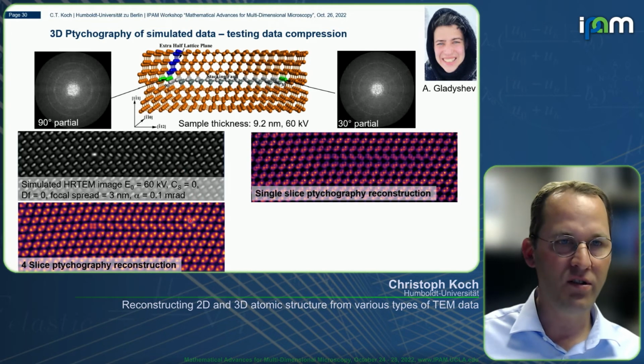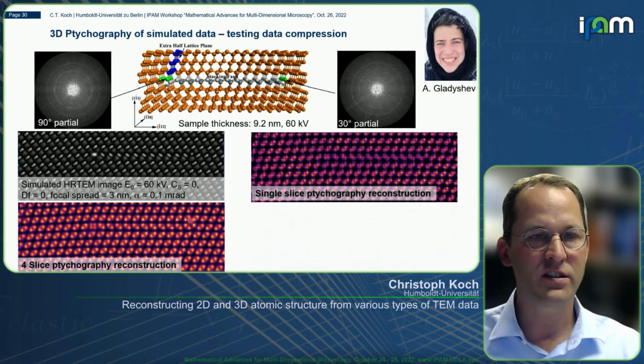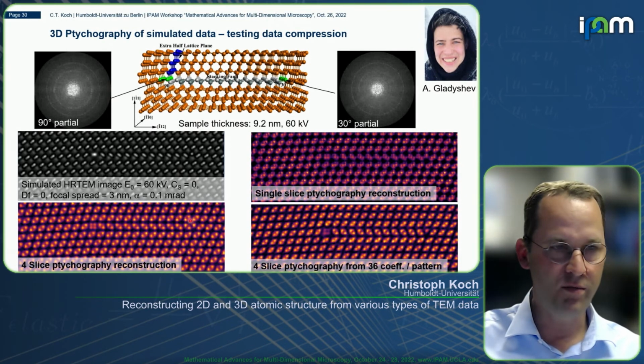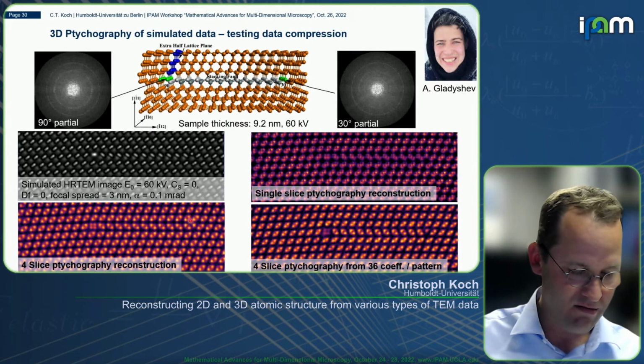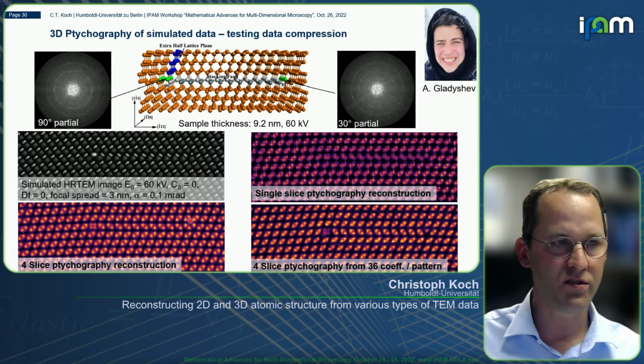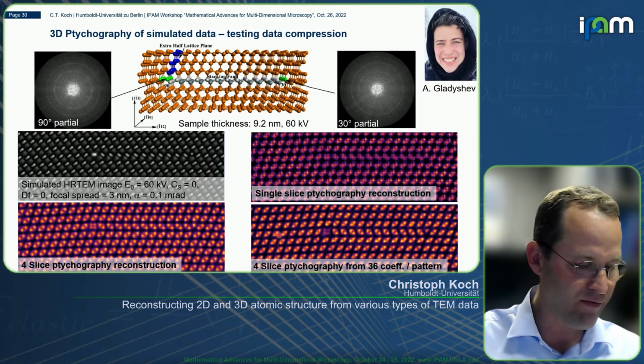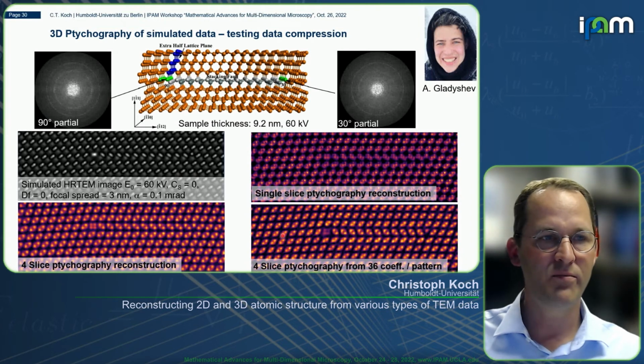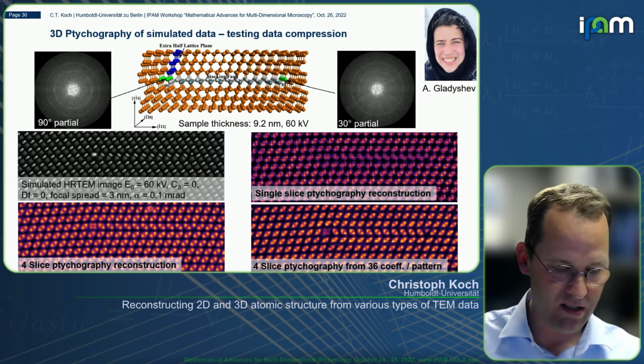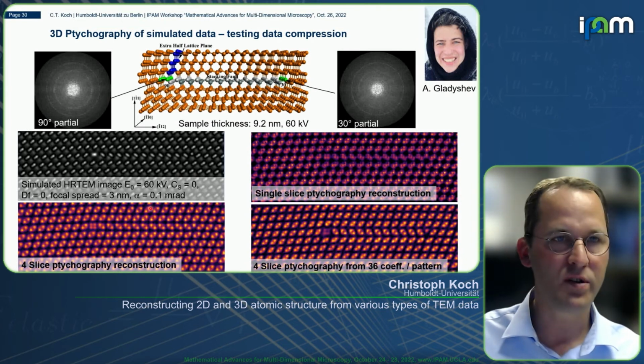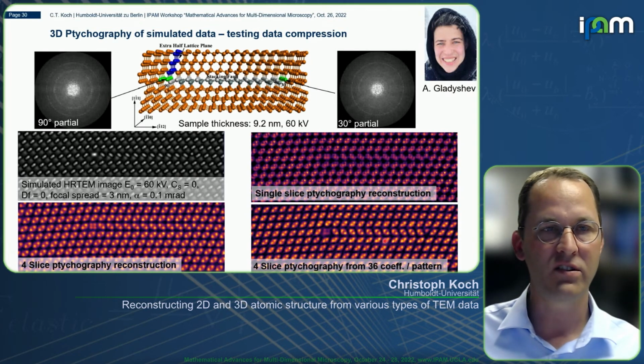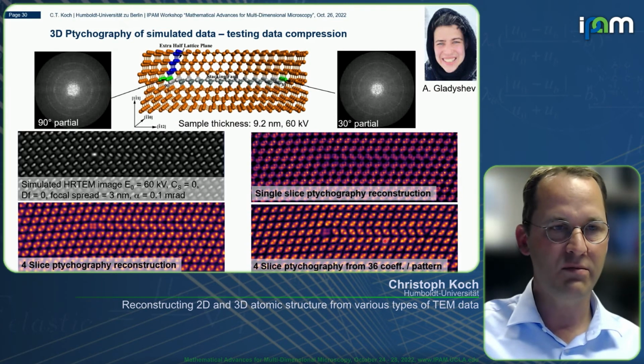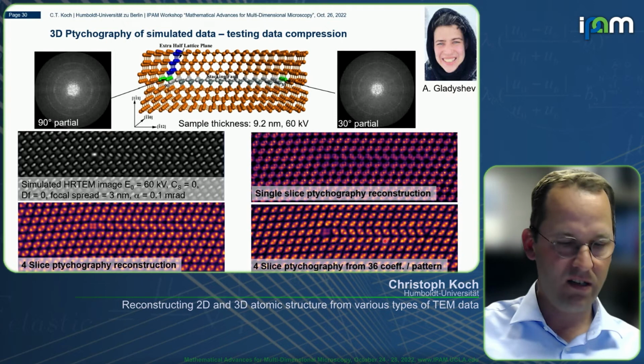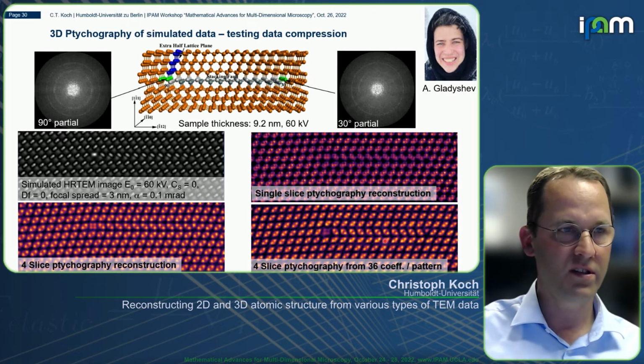But if you then keep only 36 numbers for each probe position, you still get pretty much the same reconstruction. So you can really reduce from 500 by 500, so 250,000 numbers in a diffraction pattern, to only 36 numbers per probe position, and being sampled only every 1 angstrom. This is actually just a few hundred kilobytes of data, not even a megabyte. So really, data can be reduced enormously and still get a 3D reconstruction going.